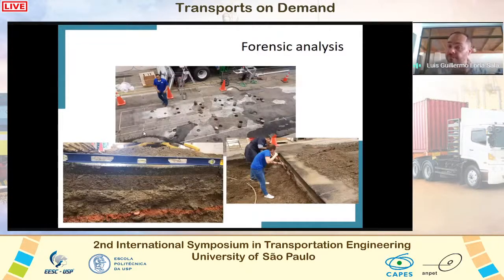We also perform forensic analysis for everything. We dig out trenches to see what was really happening with the deformation of the layers, the cracking, and the moisture damage. We tried to assess the exact condition of each one of the layers after the testing. We took cores to analyze the moduli, the dynamic modulus, and other testing.